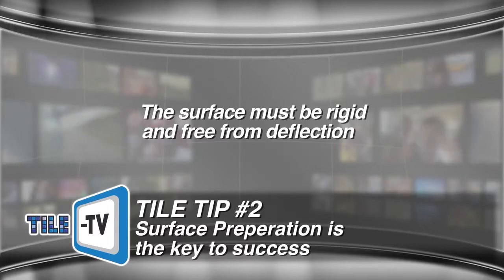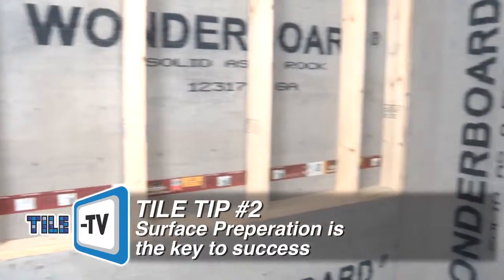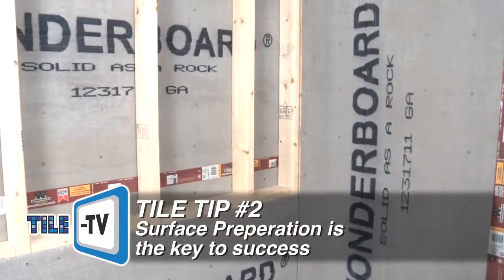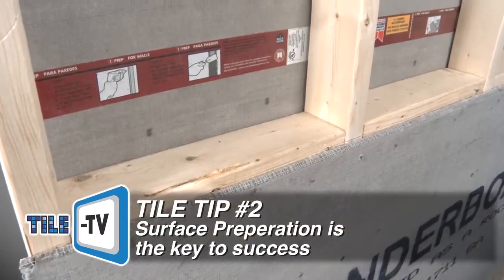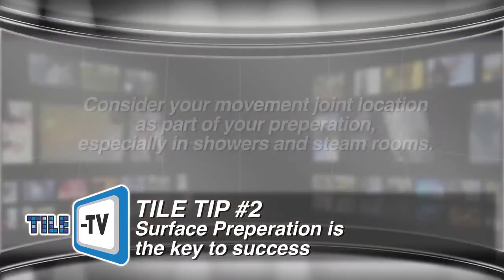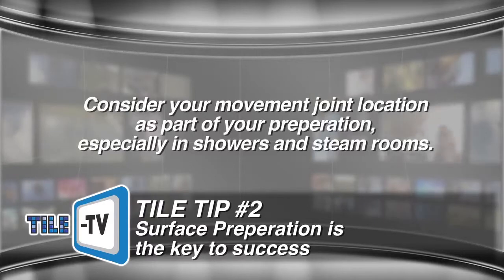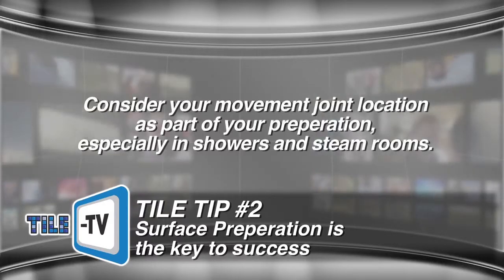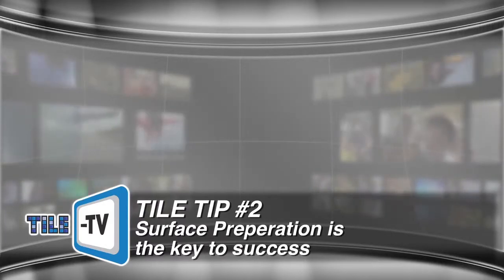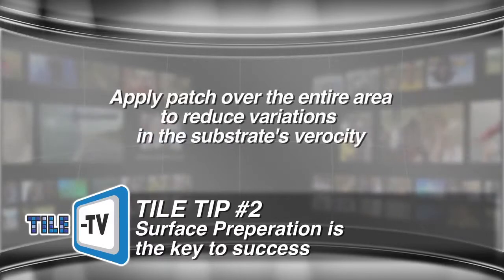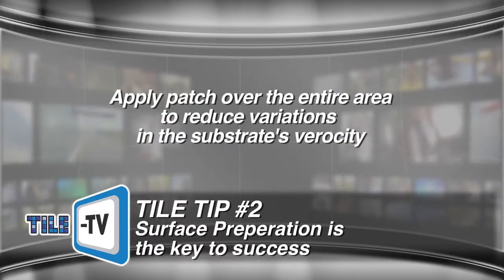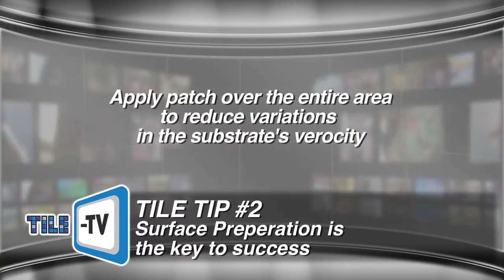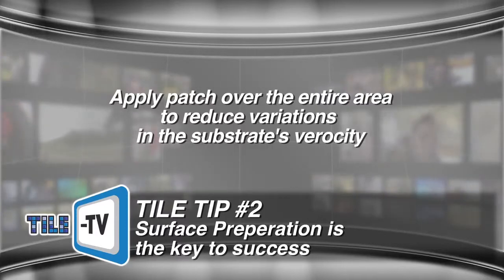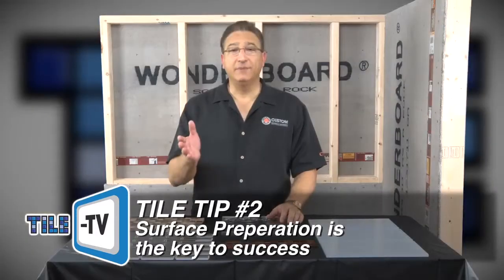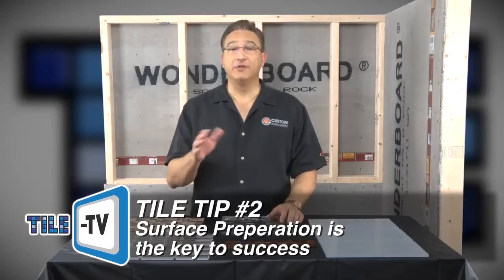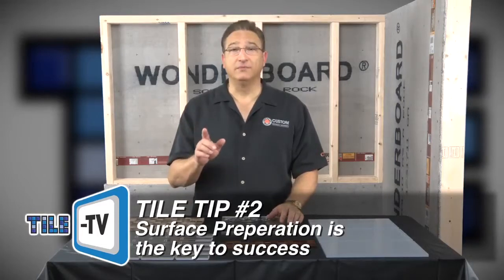Remember, we're installing glass. Consider adding additional blocking or bracing, using a mortar bed as a base for floor tile over wood framing. Consider your movement joint location as part of your preparation, especially in showers and steam rooms. And if you patch the surface, apply patch over the entire area to reduce variations in the substrate's porosity when using transparent or highly translucent tile. Check with the manufacturer to confirm if a membrane is recommended or not recommended at all.